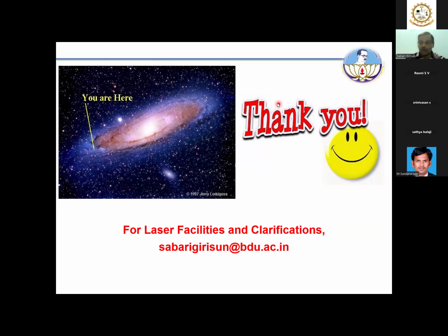Yeah, I understand your question. Due to the time limit, I have skipped some of the slides. I have not taken you deeper into the nonlinear optical phenomena. The basic difference between sequential two-photon absorption and genuine two-photon absorption can be identified by performing the Z-scan experiment with different laser pulses. Genuine two-photon absorption is a process in which, when the laser pulse energy changes, the nonlinearity does not change. Which means if I perform an experiment at 100 microjoule, I get some pattern. If I perform the same experiment at 150 microjoule, the pattern remains the same. If I do the experiment at 200 microjoule, the pattern remains the same. It means the nonlinear absorption coefficient is independent of the intensity of my light. You call this condition genuine two-photon absorption.